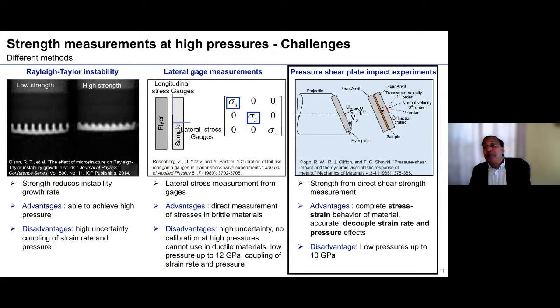In this case, you impact a hard flyer plate on a sample which is sandwiched between two anvil plates, called the front anvil and the rear anvil, and you measure the free surface response. This is oblique impact. Due to the obliquity of the impact, you generate both normal and transverse waves, and the free surface velocity profiles are measured using normal and transverse displacement interferometers. This will give you a direct measure using the characteristic analysis. One can get the complete stress-strain behavior of the material, and this way one could decouple the strain rate and pressure effects. And I will describe this technique in some more detail in a minute.